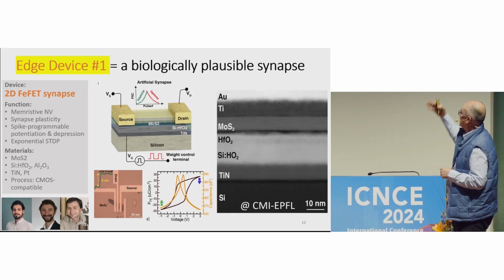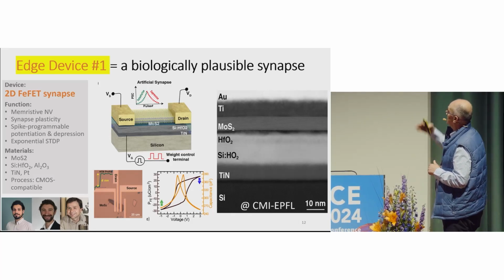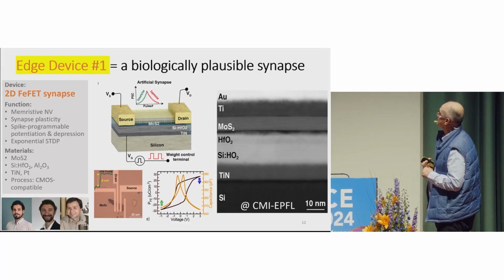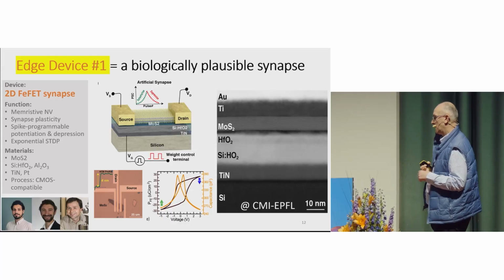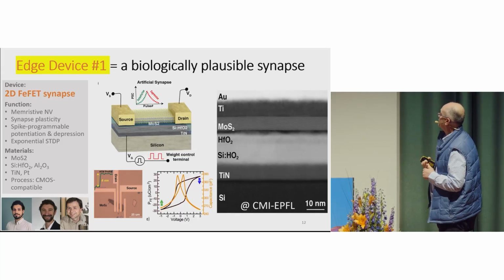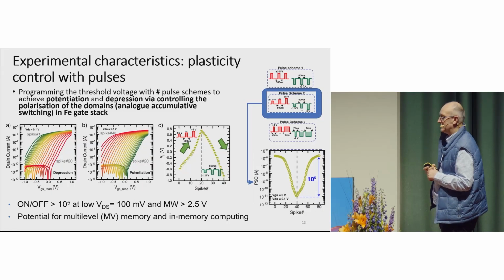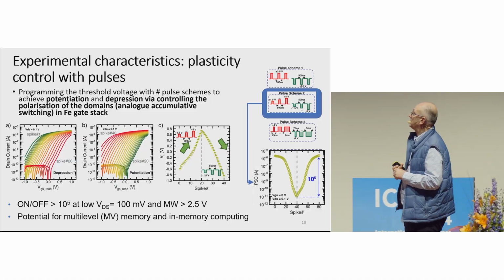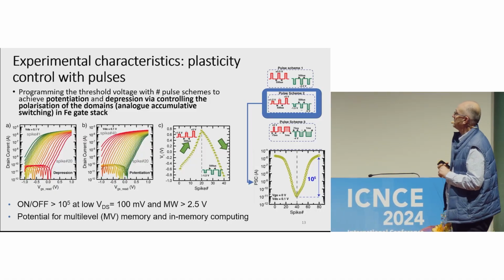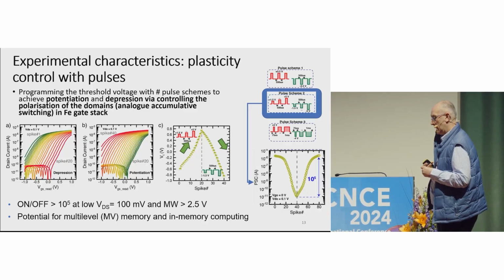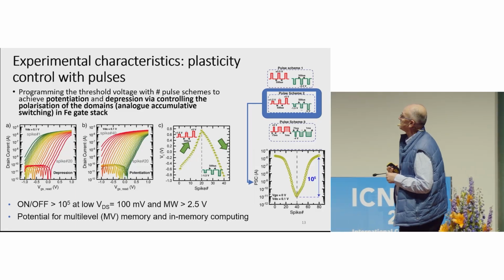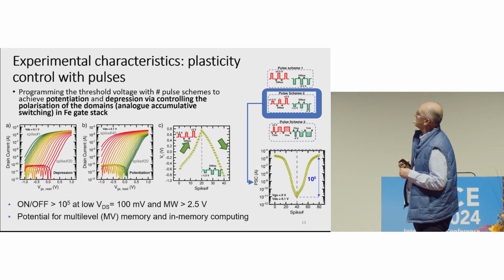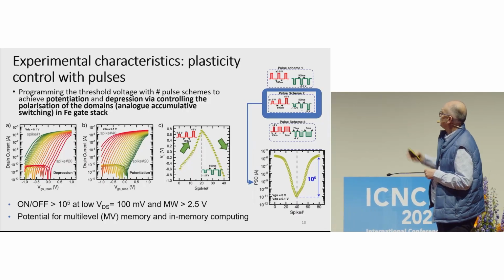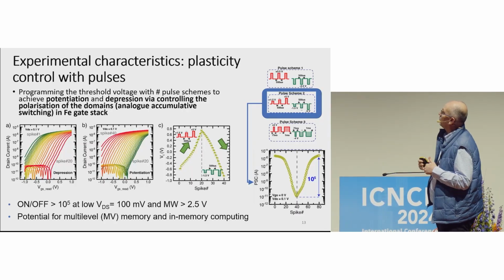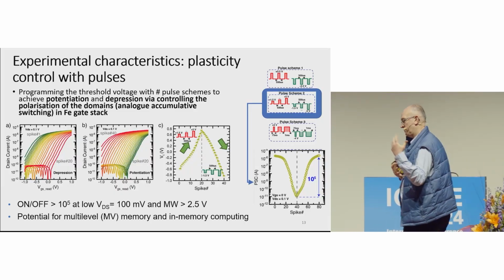And as you see here, we have developed practically this gate stack on which we transfer MoS2 from monolayer up to few layer. This is the device with few layer, and we have here gold titanium contact on top of it. And we tested it first as a memory device, but then we tried to do something that was reported recently in the literature in 2018, how to program the threshold voltage of such a device with a pulse scheme in order to achieve the potentiation and depression curve that you see here on the right by what is called analog cumulative switching of ferroelectric domain.